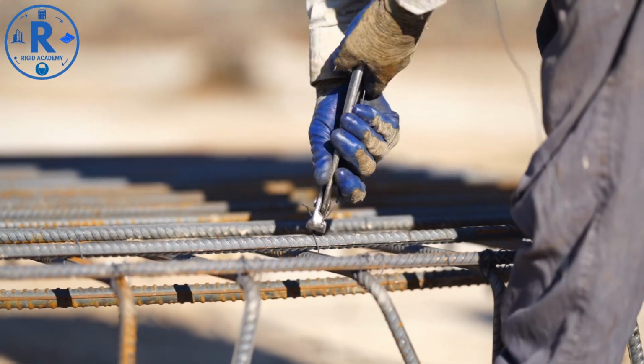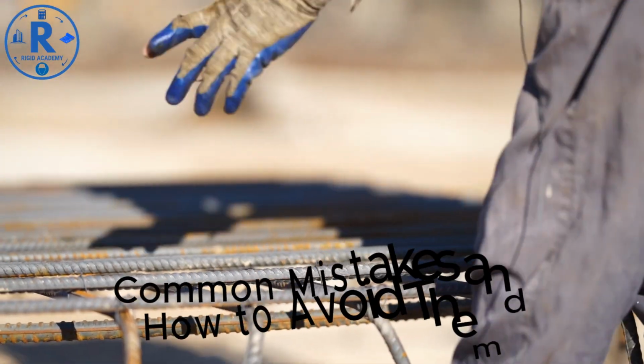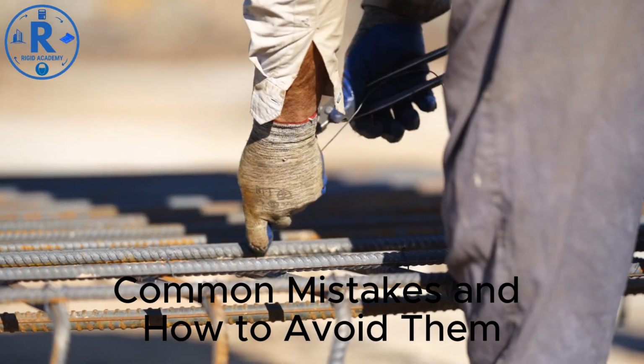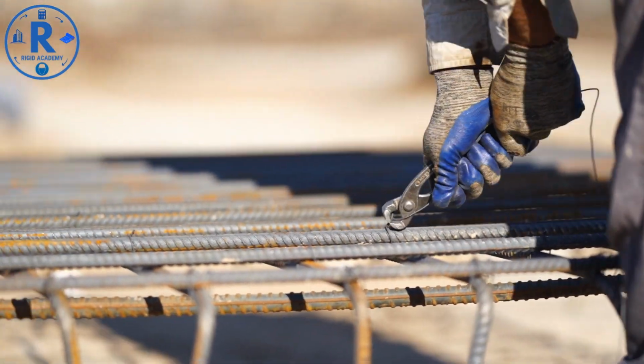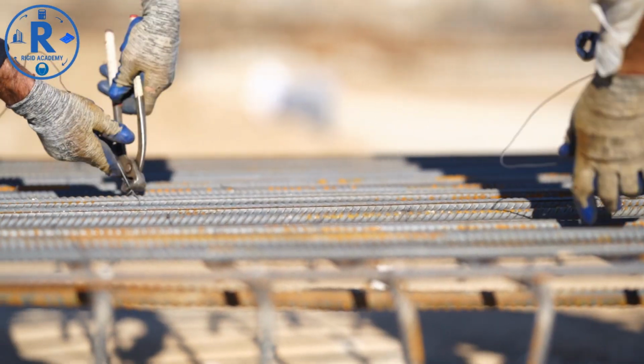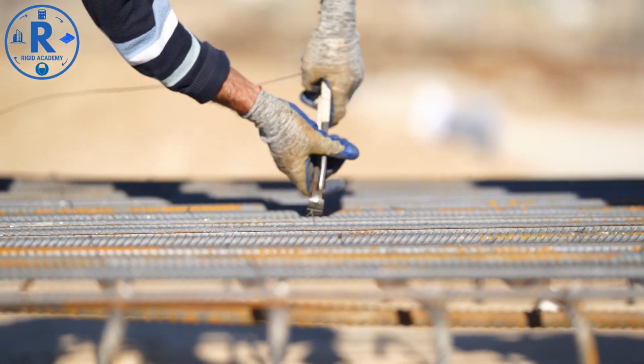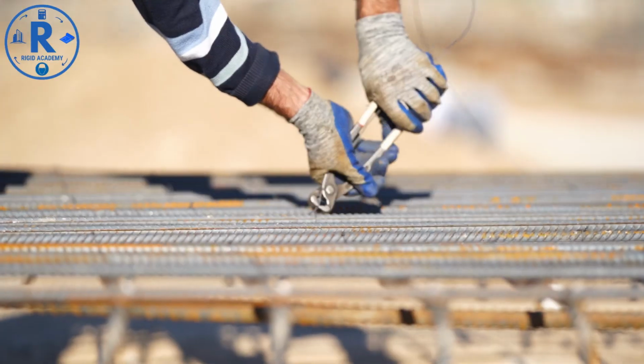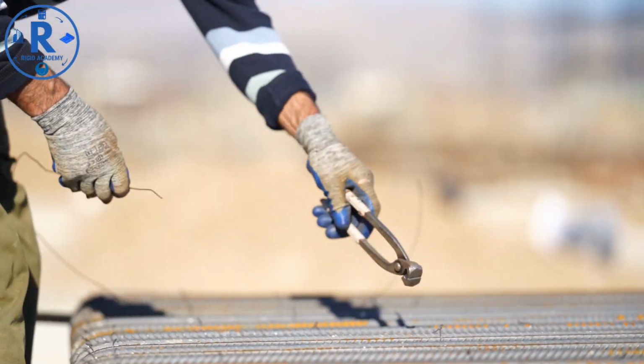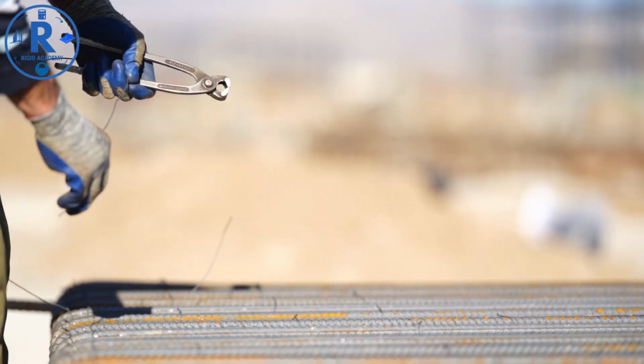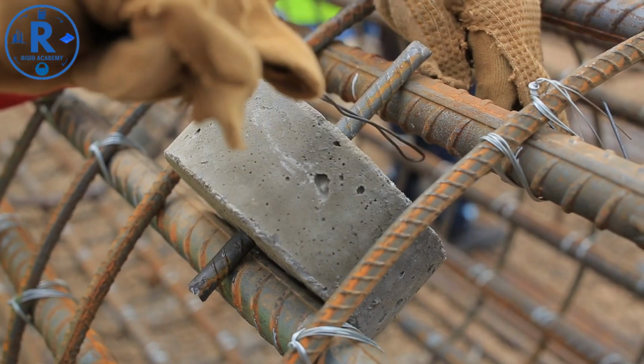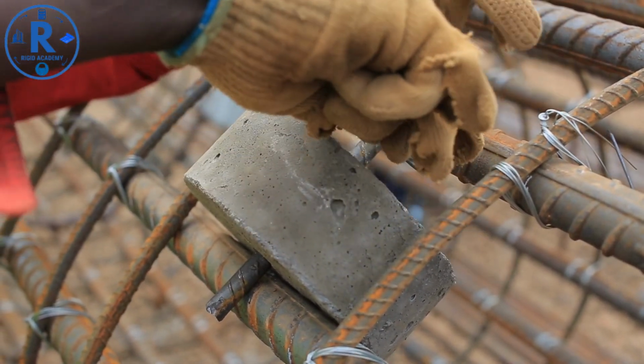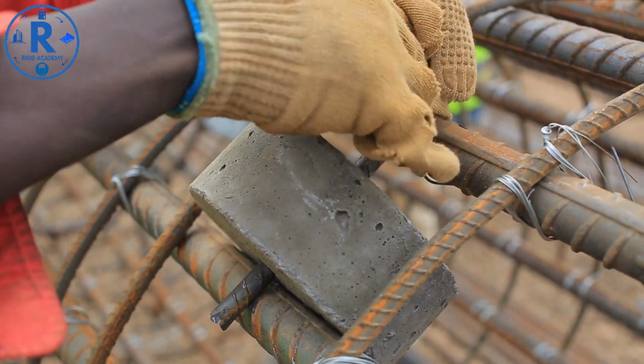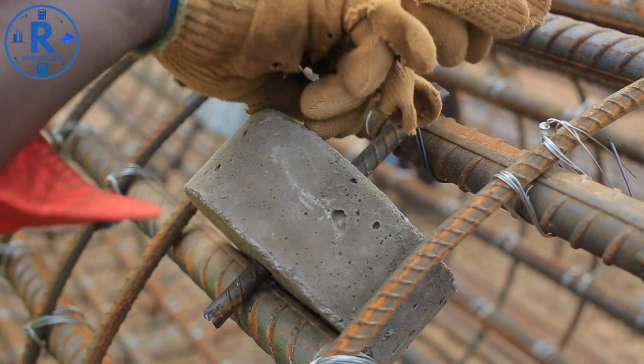Common mistakes and how to avoid them. Let's go through the mistakes most engineers make on site. Incorrect cover blocks. Using wooden or brick pieces instead of proper concrete cover blocks causes corrosion later. Improper bar bending. Sharp or inconsistent bends can reduce bar strength. Missing ties leads to displacement during concrete pour. Unstaggered laps creates weak zones.